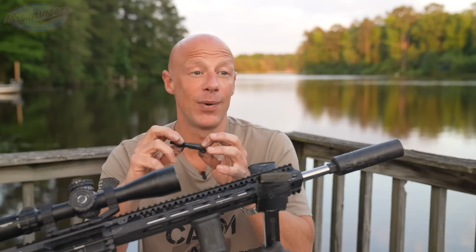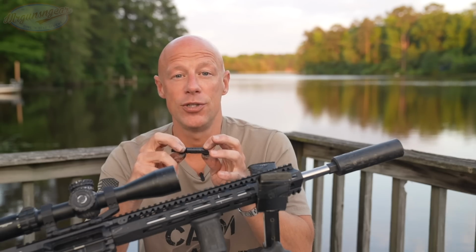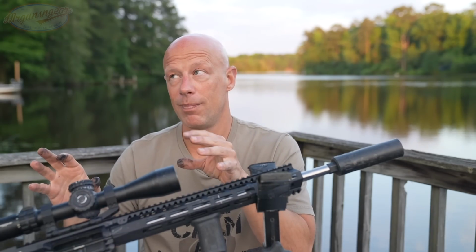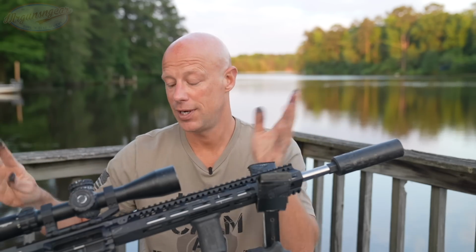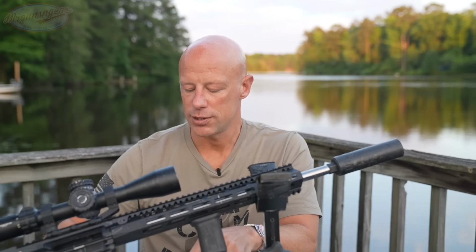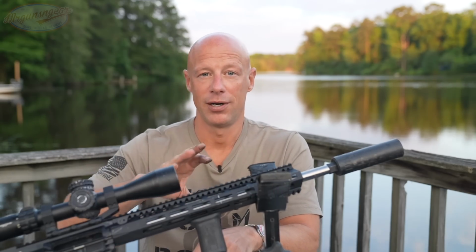And I would say that of what I've tested, probably 10% of them have had bad headspace just due to the actual nickel boron. Now, there's good ones, like there's really high quality companies that make good NIB nickel boron bolt carrier groups. I'm not saying they're bad. I'm just saying just know that it is in 2023, based on my experience firing hundreds of guns and testing at least 20 for this very issue of headspace, it can be a thing with nickel boron. So just know that. But all of the finishes that I just talked about outside of nickel boron are good to go no matter what.